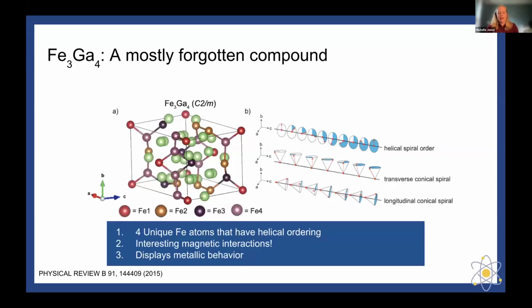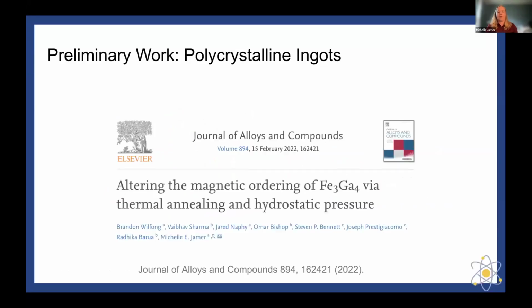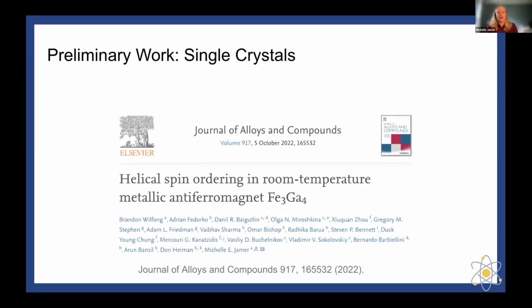The other reason why this is very interesting is because it displays metallic behavior, and we'll get into that in a little bit. The majority of the work has already been published in the manuscripts that I'm going to be talking about. The first one was in 2022, in the Journal of Alloys and Compounds. We were able to figure out how strain affected the lattice using arc melting, because at every single annealing condition, we had a slightly different strain. So we were seeing that we can tune these properties by basically adding strain and pressure. The other one that we published in 2022 was based on the single crystal work, and it's on helical spin ordering and room temperature metallic antiferromagnetic iron 3 gallium 4. So these are 2 of the main resources if you want to look into this a little bit further.